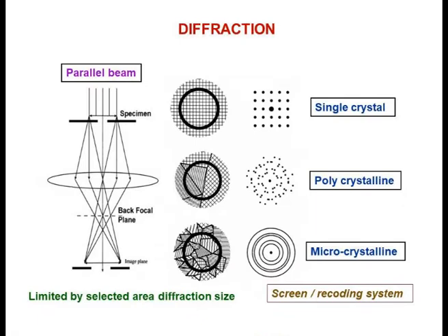Another advantage in a microscope is that we can introduce apertures at some image plane so that virtually it can choose a small region in the sample. If you wanted to put an aperture on a small region of 100 Angstrom, it's difficult. But if you put a large aperture, it acts like a virtual aperture with demagnification, so even in a polycrystalline sample we can choose a small crystalline region and get diffraction and image information from that.